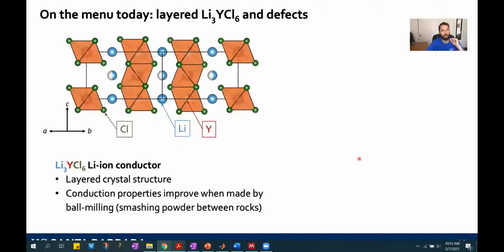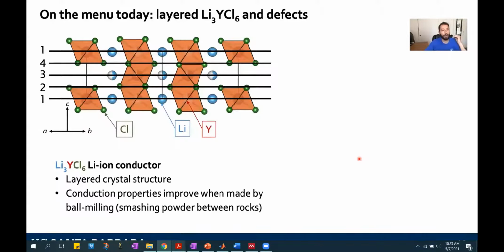Now we're going to focus on lithium yttrium chloride, and this compound is a layered crystal structure. So it's made up of a series of 4 layers where we alternate between lithium and yttrium layers with chlorine. So we build up layer 1, 2, 3, 4, and then we repeat with layer 1 stacked directly on top. This material's conduction processes improve when we make it via ball milling.